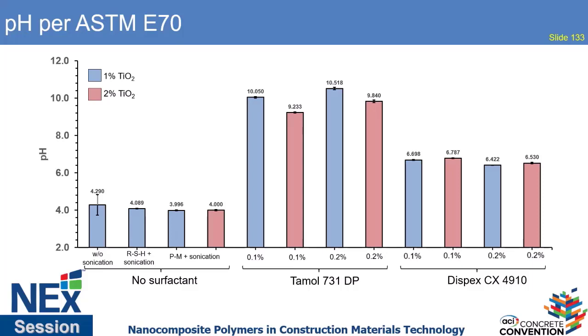Similar with the Dispex CX4910, however not to the degree as with the Tamol, we see a similar trend, only here it's reversed. The pH increases slightly as the amount of titanium dioxide increases.